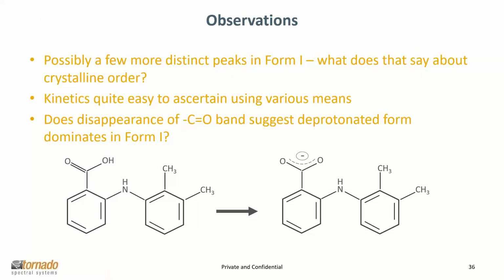So there's some interesting observations that you can make with the Raman data through this process. There's possibly a few more distinct peaks in form 1. What does that say about the crystalline order? The kinetics are quite easy to ascertain. And one of the more interesting molecular level observations that we can make is that there's a disappearance of the carbonyl band, which suggests the deprotonated form perhaps dominates in form 1.